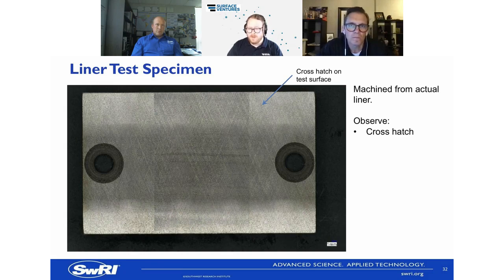A very similar question in that vein from Chris, who asks, do you have a sense for how the results would vary at different RPK values? Well, what I believe we can do is take the RPK down much lower. In fact, when the engine goes back together for the next test, we're going to begin with an RPK of 5 to 7. So we're going to target that already run-in surface roughness, and then begin from that to see if the coating is still able to have that immediate break-in even without the initial roughness.